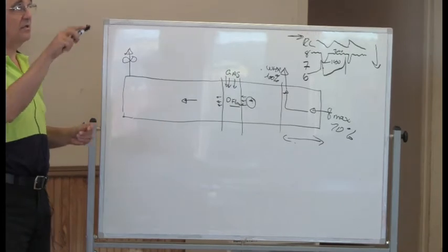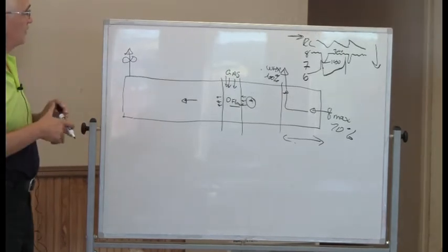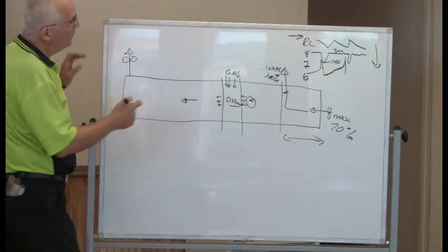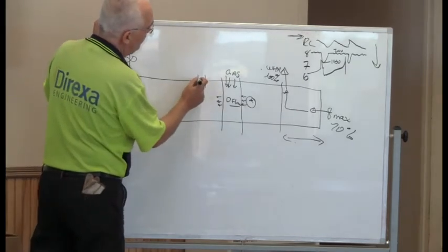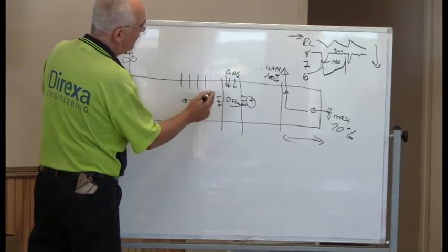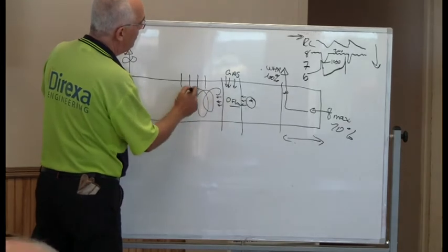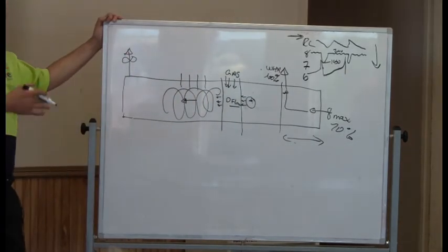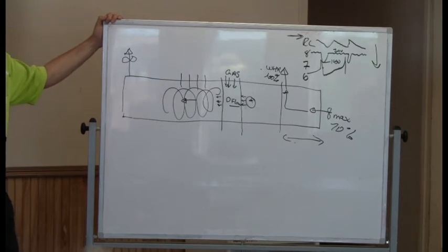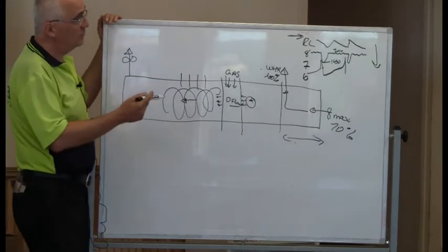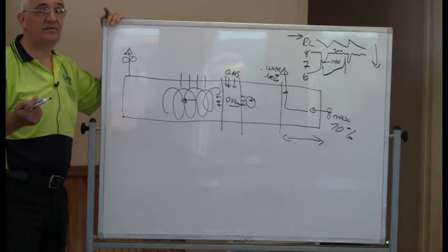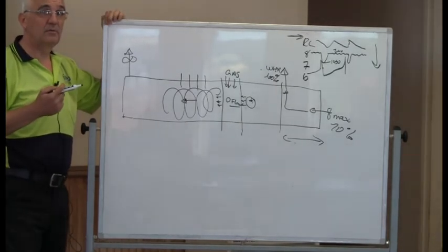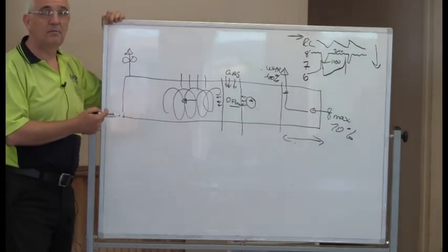Now the next trick I'm going to talk about is when you have your stick burners, of course you're going to roll smoke. You are not going to pull it like crazy, but you are going to roll that smoke. You want that smoke, which is unburned gas, to burn, but in the kiln.